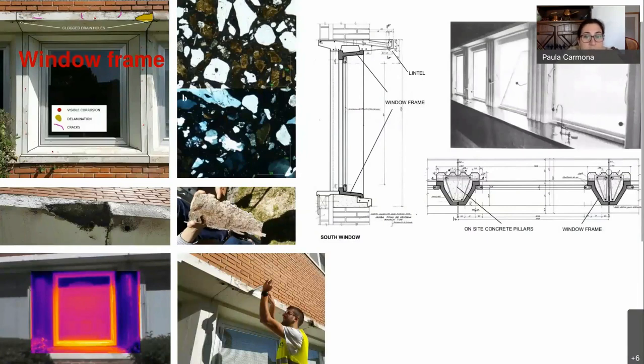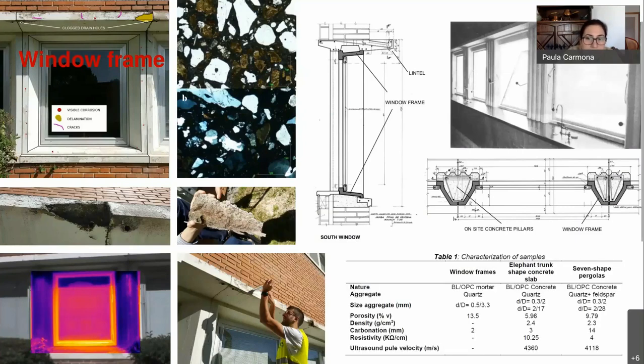The surface hardness was also measured with the Schmidt hammer, as you can see here at the bottom of the slide. We also characterized the homogeneity of the samples with an ultrasonic tester. We determined the ultrasonic pulse velocity and also the modulus of elasticity. And through infrared thermal imaging, you can see here in the image of the window, we spot heat losses to map moisture distribution. And next, please.